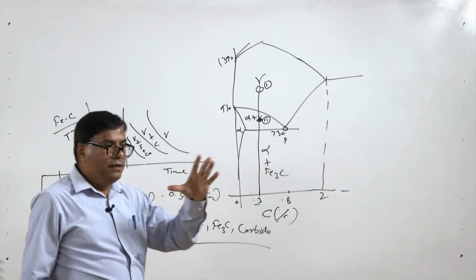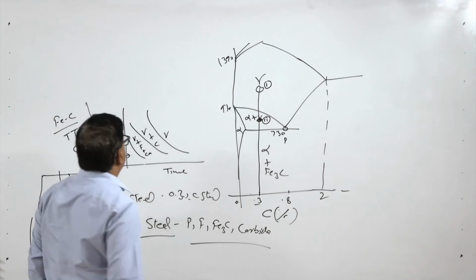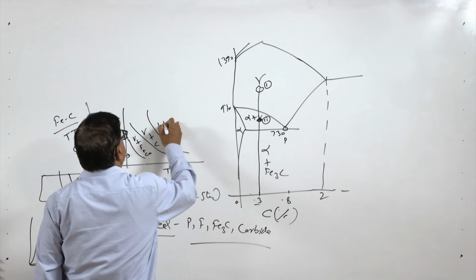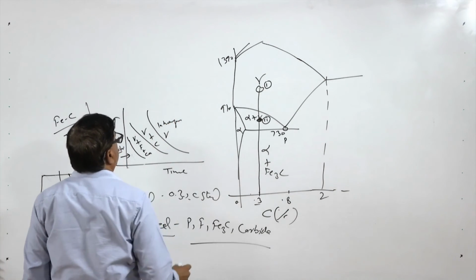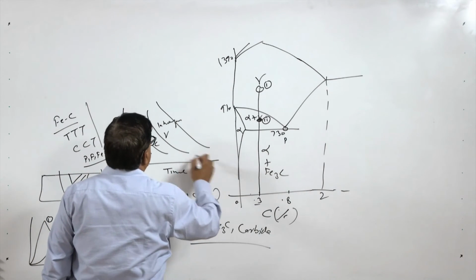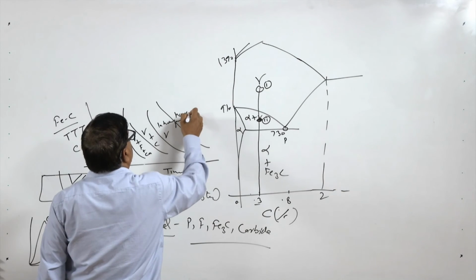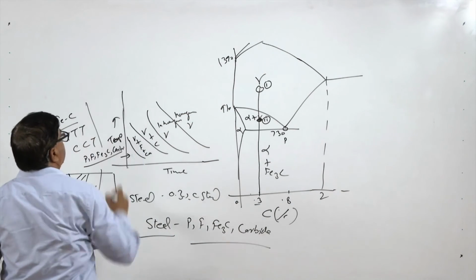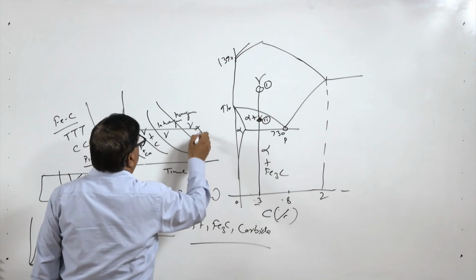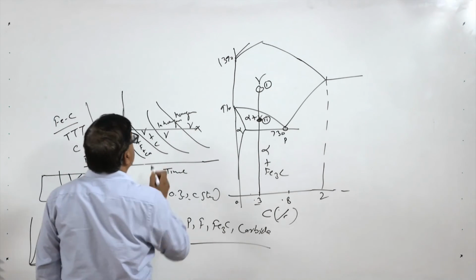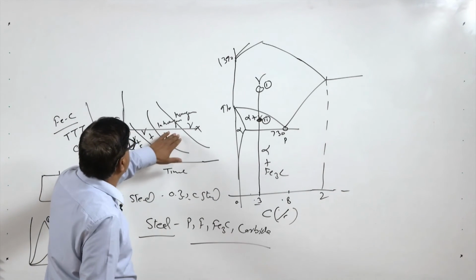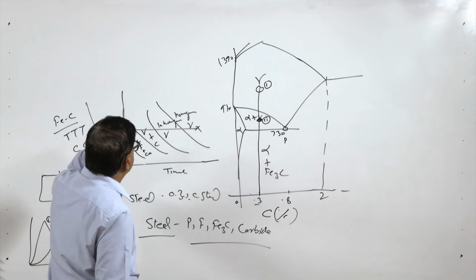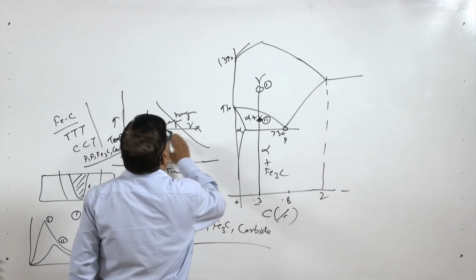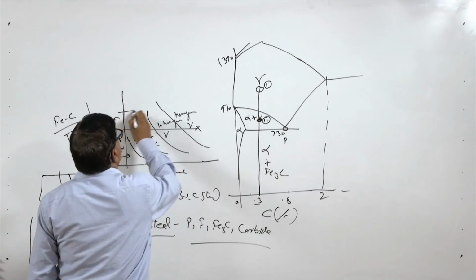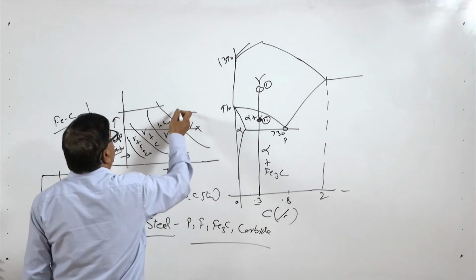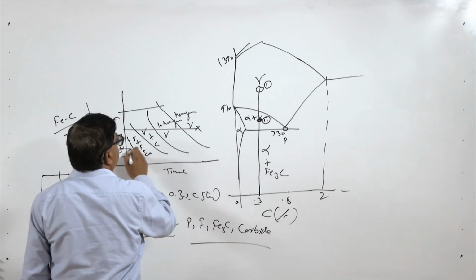Wherever carbon content is high, that will have a higher concentration of carbon as compared to the other areas. So, this is inhomogeneous austenite, and if the heating continues for further long, then we will have the homogeneous austenite. If you see this diagram, to have the homogeneous austenite it takes long, and if it is just plain carbon steel, then this much time it will take, because in this case we will not have the carbides. If the temperature is high, it takes a shorter period to have the homogeneous austenite, and if the temperature is low, then it takes long.